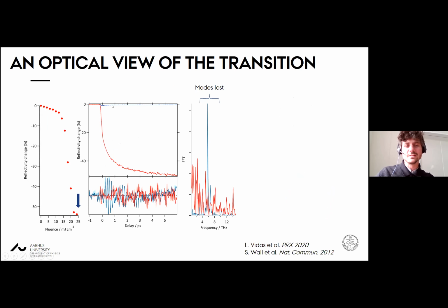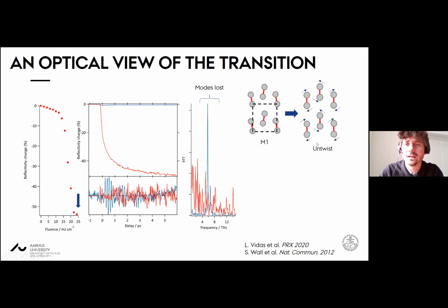Okay, so when we excite the system harder, we see a loss of these coherent phonons. And the reflectivity instead shows very different dynamics. So just a small, slow and gradual increase in this particular case. It depends a lot on the fluence and the wavelength. But most importantly, we see there are no phonon modes in the system anymore. And the question I've been asking myself since 2012 anyway, is whether these oscillations carry on to drive the transition, but we can't see them, or if something else is going on. So at some point, when we drive the system optically, we can't see the phonons anymore, but we don't really know what's happening.